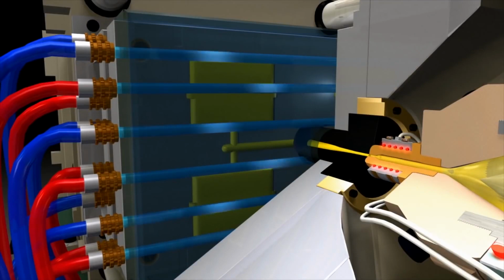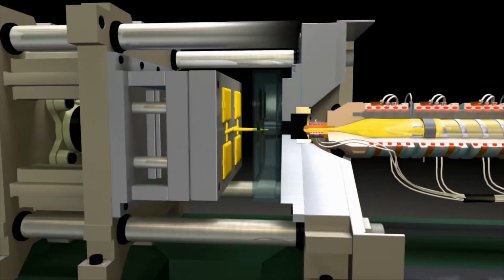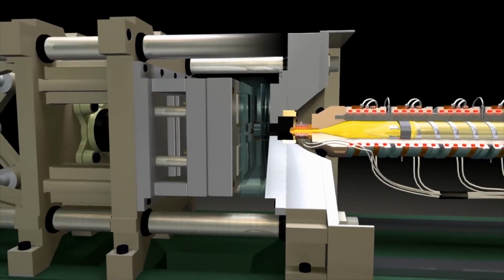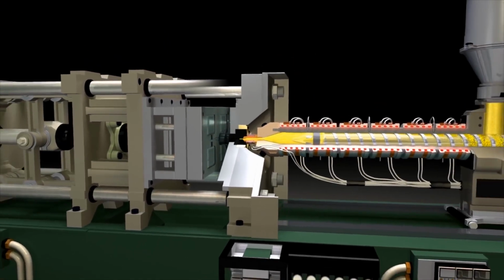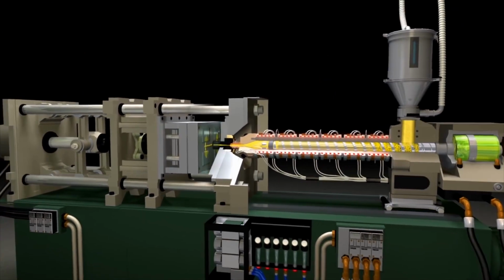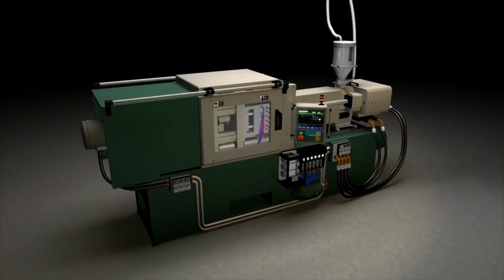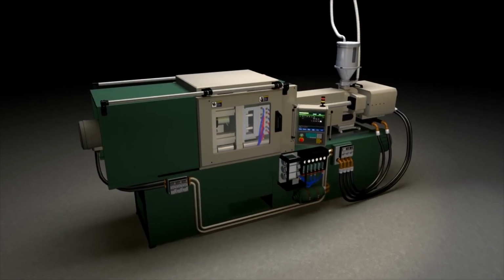ANOVA shows the best combination of factors and provides the optimal combination of plastic injection molding parameters. The importance of parameters was presented as a percentage of contribution to each defect. Using warpage as an example, the melt temperature, the packing pressure, the mold temperature, and the cooling time play the most important roles.